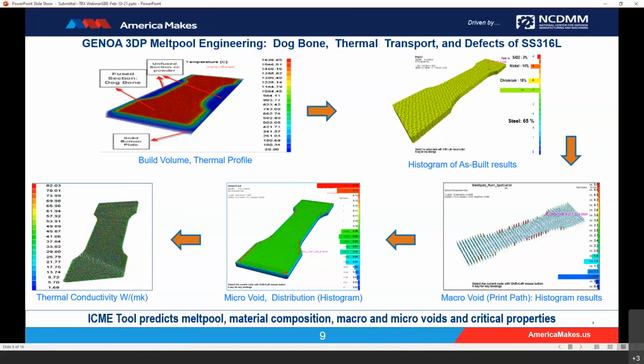The figure on the upper left shows the build volume and thermal profile of the dog bone specimen with fused and unfused powder in the bottom plate clearly displayed. The upper right image is the histogram of the as-built specimen and highlights the composition of the material, including precipitates and inclusions corresponding to the SS316L. As you can see at the top right, the presence of the silicon oxide and the chromium.